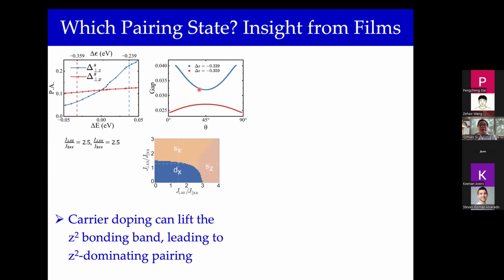So for example, here are the two cases. In one case, the pairing amplitude of the z-square orbitals dominates. Theta 45 degrees is a diagonal in the square lattice notation. And so the different orbitals contributing to the pairing lead to a gap variation on the Fermi surface that has a reasonably substantial amount, but it goes this way. But in the other regime, which corresponds to here, the variation goes the opposite way. So that's a testable statement.